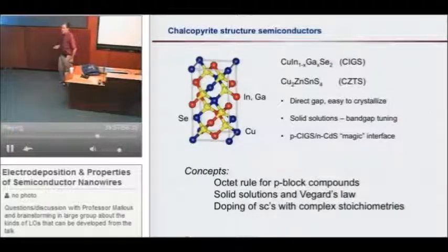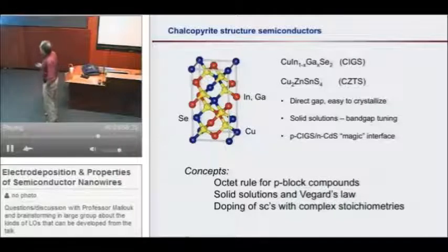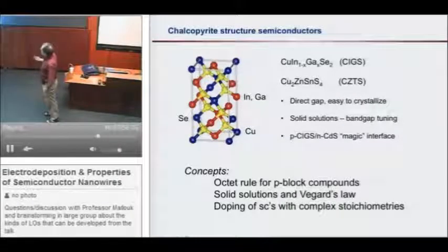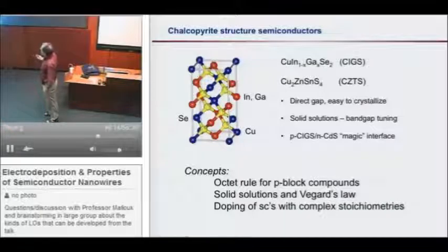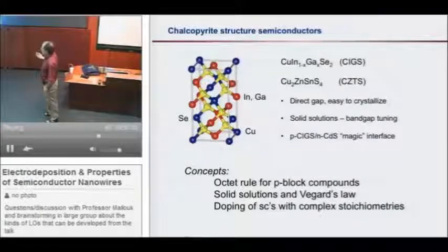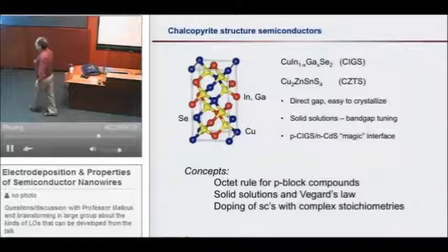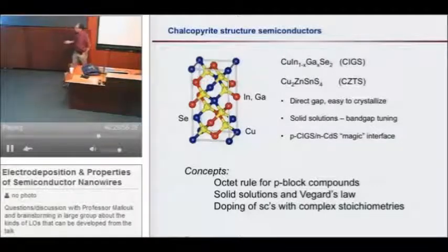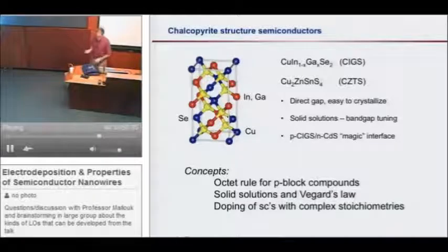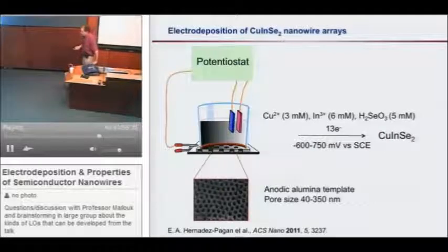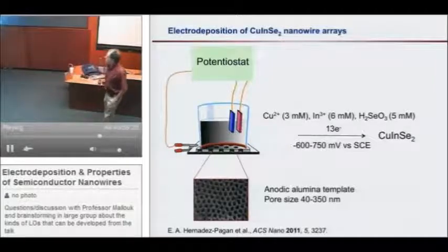But not before we decided to do a project on chalcopyrites, which we heard about yesterday. Amy talked about this one. There are lots of good reasons to work on this. We were interested in CuInSe2 because it's a really wonderful material. It has a band gap of 1.1 eV. It has a basically very forgiving interface with cadmium sulfide. You can make pretty junky CIGS. As Amy showed, polycrystalline electrodes are now getting 17, 18 percent efficiency. Basically what we did was grow them as wires. Electrochemistry is a cheap and scalable technique for making stuff.